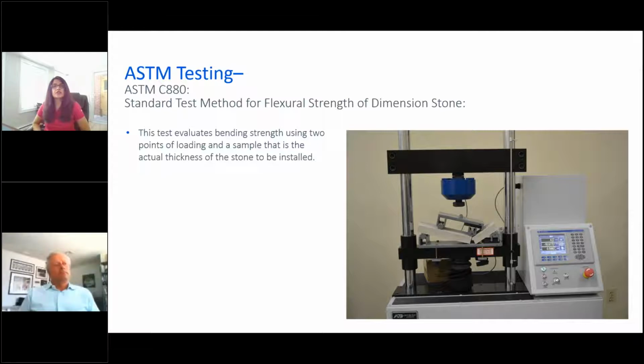ASTM C880, the standard test method for flexural strength of dimension stone. This test evaluates bending strength using 2 point loading and a sample that is the actual thickness of the stone to be installed. So you basically test the stone for flexural strength based on its actual dimension. Let's say the stone is used for just 1.25 inches. We will only use that thickness for that particular project to test it. And as we are changing these facades, more and more thinner stones are utilized in all these buildings, and this test becomes really important in order to come up with an actual safety factor to be used for safe installation.